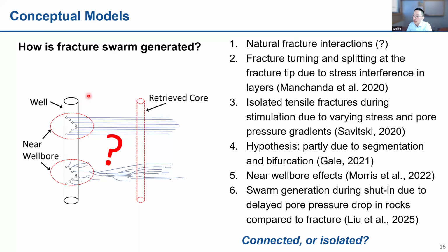The big question here is, how is the fracture swarm generated? Over the past few years, especially after the observations at the Eagle Ford and Midland, there are a few conceptual models. First, natural fracture interactions. This one is likely to be ruled out because, for example, at the Eagle Ford Formation, according to the authors, it's a region where the natural fractures are relatively sparse, a so-called quiet fracture zone. So it's not likely that natural fractures have a big impact on the swarming behavior. Also in the Midland, although there are a few sites of natural fractures, most of them are cemented. Based on the first part of the presentation, we know that if the fracture is fully cemented, then the natural fracture also has limited impact. So this factor is likely to be ruled out.